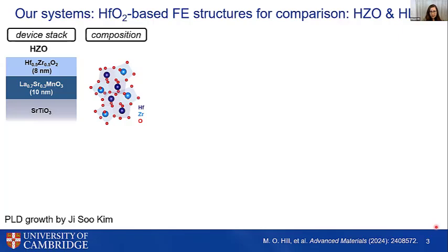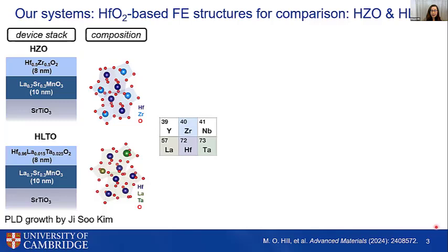And then to compare to this, we also made a more novel form of hafnia composition, which is hafnia that's doped with lanthanum and tantalum. This is grown in almost the exact same fashion with PLD, where we grow 8 nanometers on the same thickness of LSMO and strontium titanate. The goal here was to create something very similar to HZO, in that we'd have a balance of lanthanum and tantalum dopants that would charge compensate for the hafnia, because hafnia and zirconia themselves make a charge compensated film.